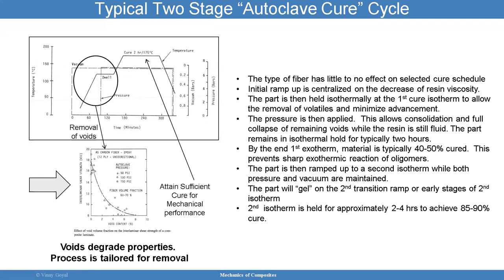We covered that. By the end of the first exotherm, the material has been cured to some extent, 40 to 50%. And then we ramp it up again to a second isotherm. And the idea there is to start gelling the materials on the second transition ramp we see there at the early stage of the second isotherm. And then you can hold it there for 2 to 4 hours to achieve most of the cure in this time period.